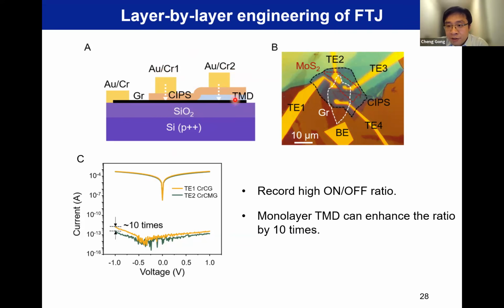The two devices differ only by the presence of one monolayer transition metal dichalcogenide, here molybdenum disulfide. You can see the on-state current is not changed much, but the off-state current was further suppressed by 10 times due to the presence of such a gapped semiconductor between CIPS and graphene. So this shows the engineering of the electron tunneling pathway is really layer by layer. This is physically very intriguing, and it also gives an enhanced on-off ratio, so that goes to 10^10. As I said, this is at least 4 orders of magnitude higher than the best resistance ratio for oxide-based ferroelectric tunnel junctions. And again, this is demonstrated at room temperature.